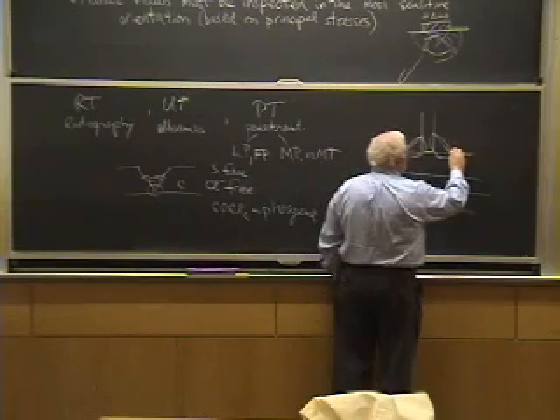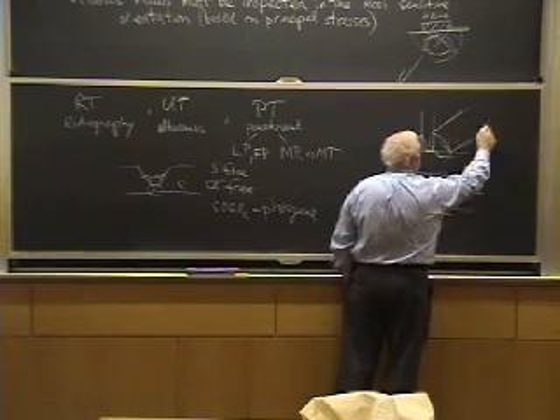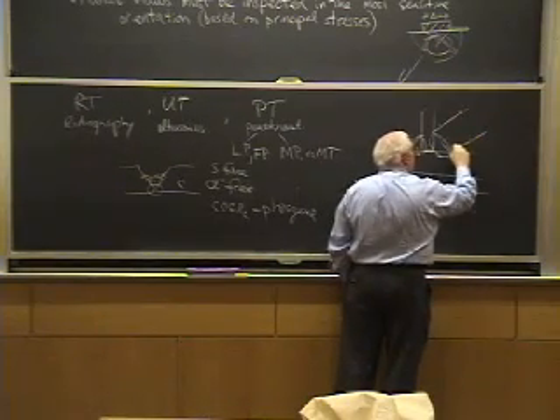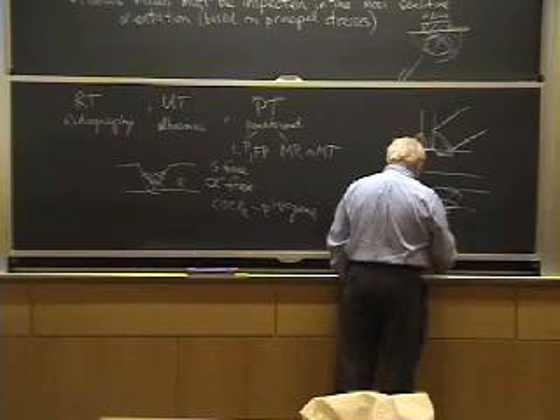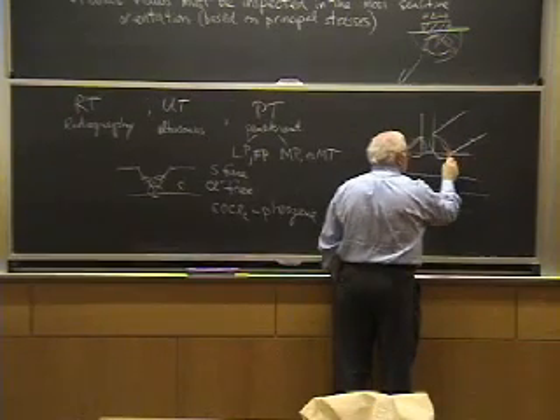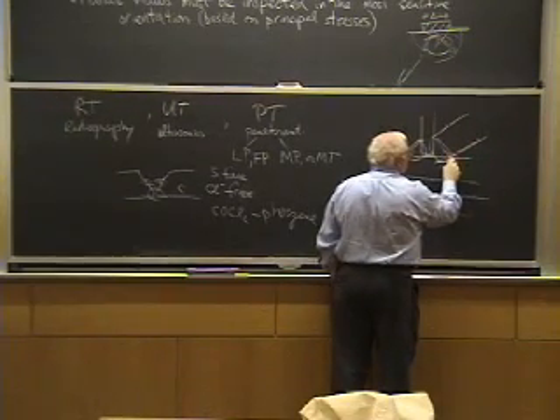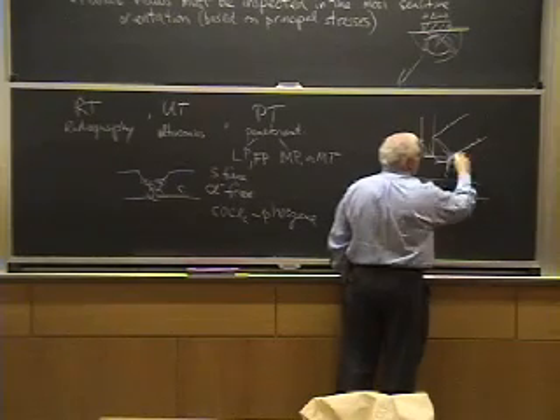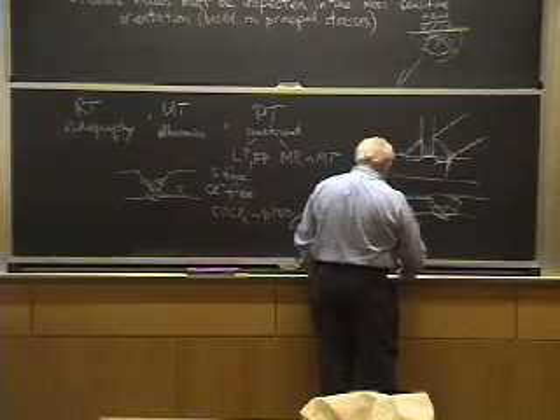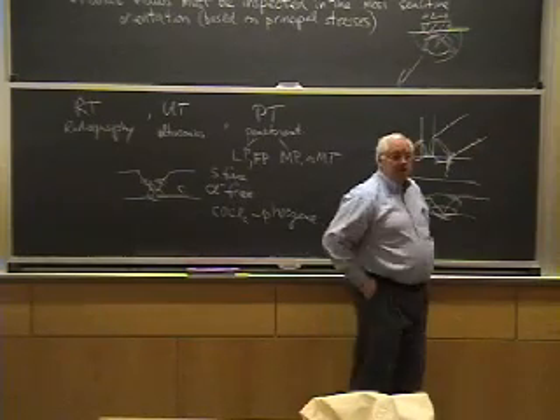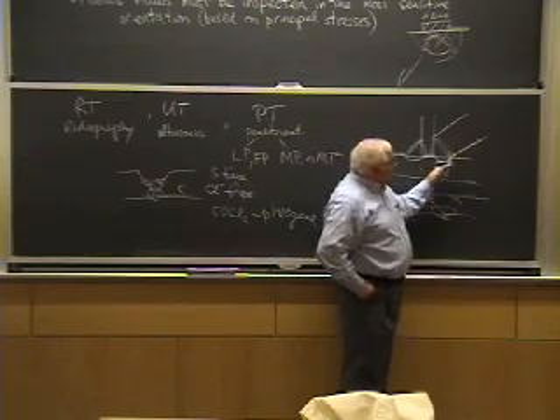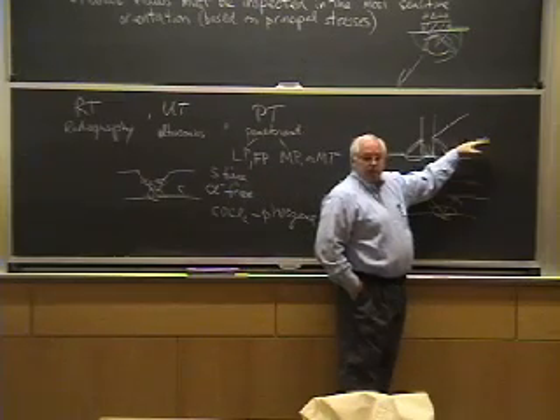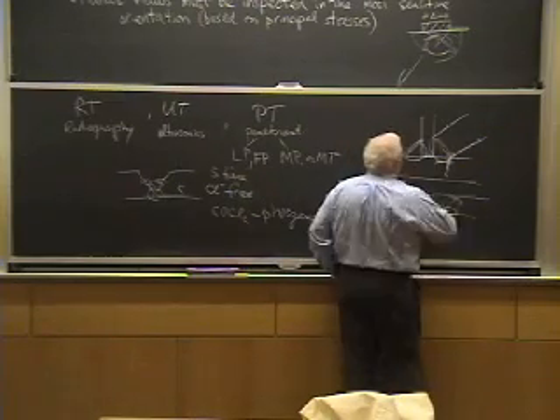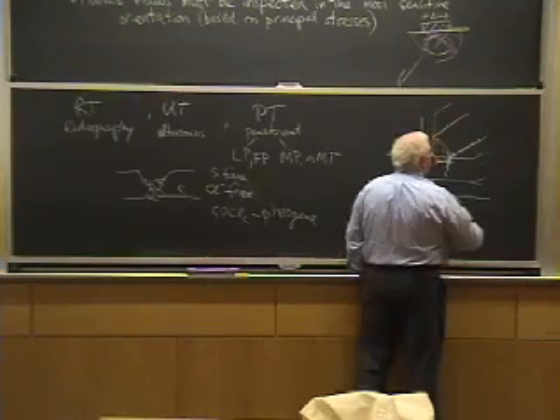So typically what they will do is they'll do magnetic particle. And what you're looking for usually are toe cracks. A crack that comes right down at the toe of the weld and runs into the material. And magnetic particle loves something like that. You know the orientation of the crack. It's going to be running right along the toe of that weld in 3 dimensions.